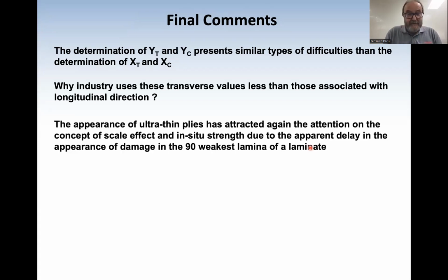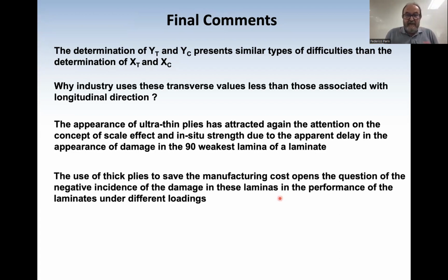The appearance of ultra-thin plies has again attracted attention to the concept of scale effect and in-situ strength, due to the apparent delay in the appearance of damage in the 90 degree weakest lamina of a laminate. The use of thick plies, which is very attractive from the point of view of saving manufacturing costs, opens the question of the negative incidence that the damage in these laminas may have on the performance of the laminates under